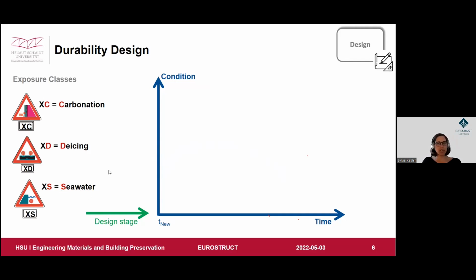And we are very used to just choosing the concrete composition or the concrete cover depth, which is assigned to each exposure class. This is how we have done it for years now in Europe, and we apply it, and we do not think about corrosion anymore. But to ensure at least a minimal nominal condition, we do not really know. The exposure classes tell us nothing about a real service life. We cannot say what is really the availability of our structure, what is really the service life, and we have no idea how the condition behaves over time.